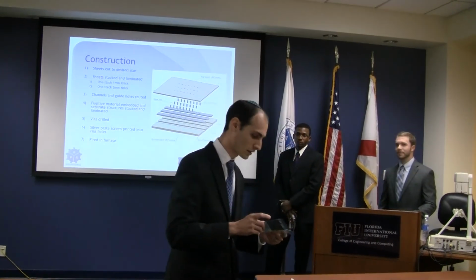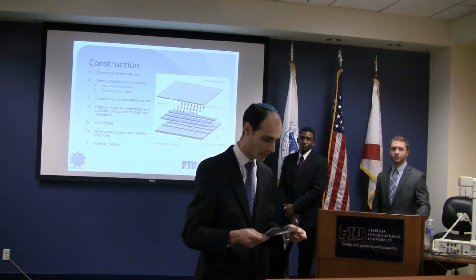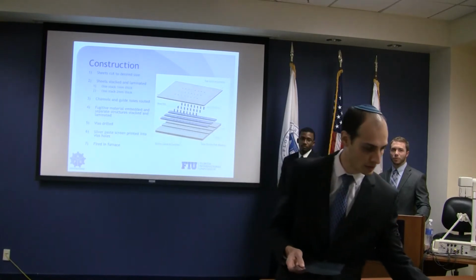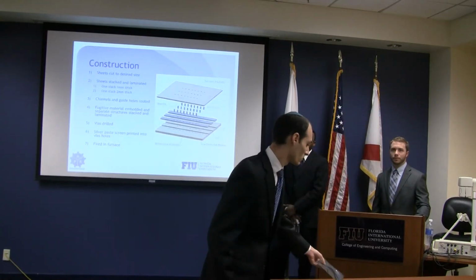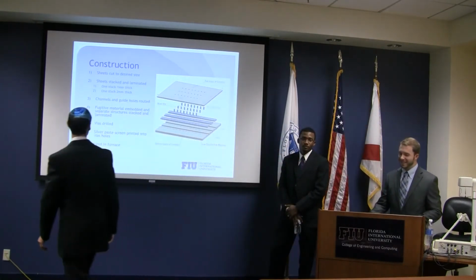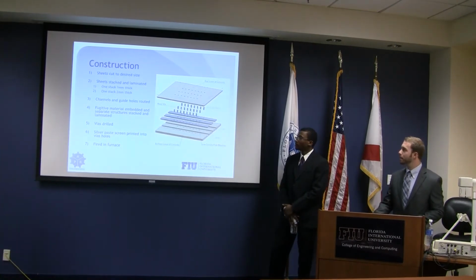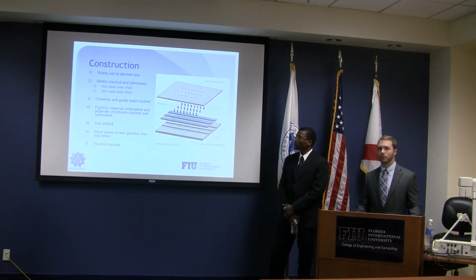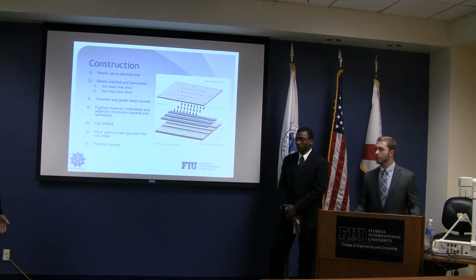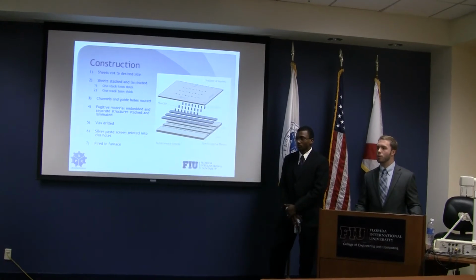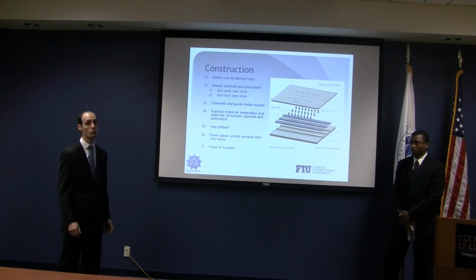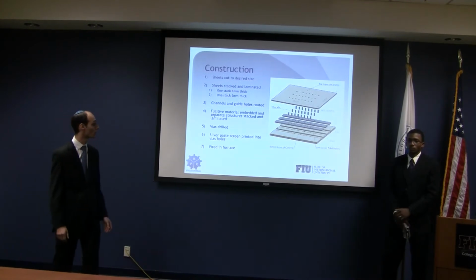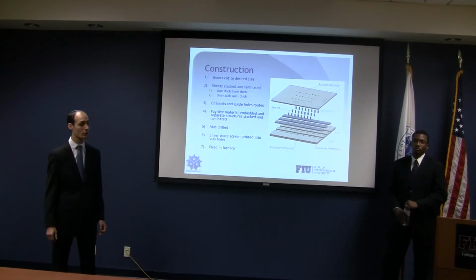And it's called green before it's fired. And this is our Regolith green tape. With those tapes, we cut them to the proper size. We would peel them off of the mylar on the back and stack them into 1 millimeter and 2 millimeter thick stacks. That's 10 and 20 different layers of them in order to do that. Once we did that, we pressed it, as was said before, and we routed out the channels.